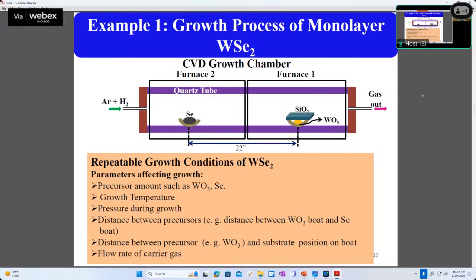So for growth purpose, what we do basically, we take tungsten trioxide in one boat, and on top of that we keep silicon oxide material, and then in another boat we keep selenium, and argon and hydrogen are used as carrier gas for this. At suitable temperature, if you heat furnace 1 and 2, this selenium and WO3 vaporize, and they react at the silicon oxide surface, and the tungsten selenide material is formed. Whatever the exhaust is there comes out from that side. So this is basically a quartz tube system.